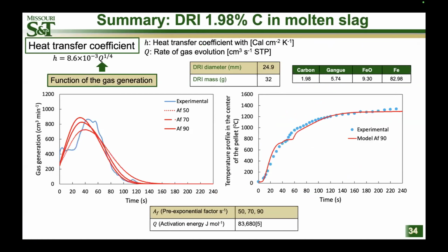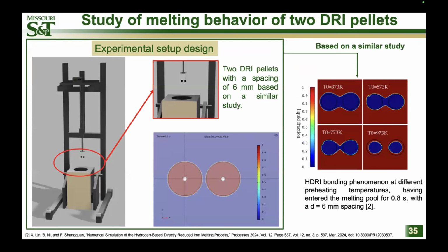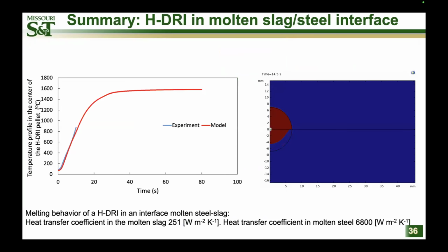We also model the gas generation in the pellet, and the off-gassing in that pellet is then tied to the heat transfer, and we've developed some heat transfer correlations to relate the volumetric gas evolution to the enhancement of the heat transfer coefficient and convection. We're also modeling more complex situations with multiple pellets and pellets at the slag metal interface to study how these melting behaviors might occur in these different environments.